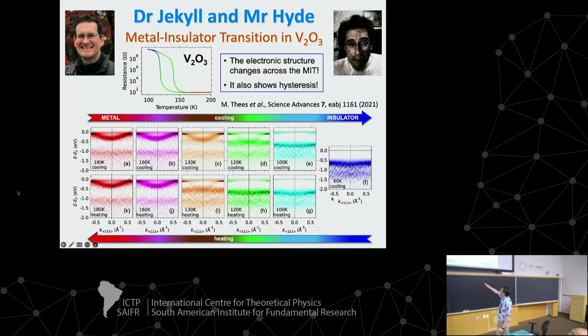system is observed. Compare, for instance, 120 Kelvin, 120 Kelvin, and 130 Kelvin in the cooling and heating cycles. And the relative intensities of both states are completely different. Okay, so that's it. That's the experimental answer.